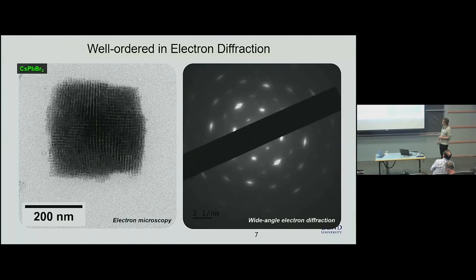When we looked at wide-angle electron diffraction, we noticed something remarkable: instead of diffraction arcs that one would expect, we saw pretty much very narrow arcs, almost spots, which corresponds to quite a remarkable crystallographic orientation of nanocubes with respect to each other.